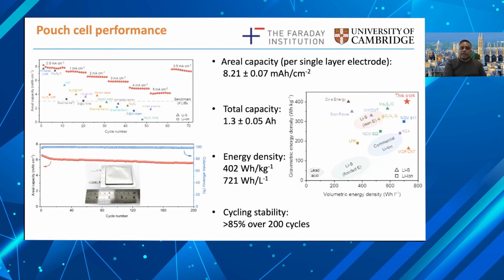So it's quite exciting that this 1T phase MoS2 works so well as a sulfur host for lithium sulfur cathodes. And the cycling stability is also quite good. It's over 85% for over 200 cycles. So there's a lot of potential for using these metallic 2D TMDs for different types of batteries, lithium sulfur batteries, perhaps even lithium ion batteries. If one thinks rationally about the challenges facing the different devices, then one can specifically target those challenges with the metallic phase of these TMD compounds.